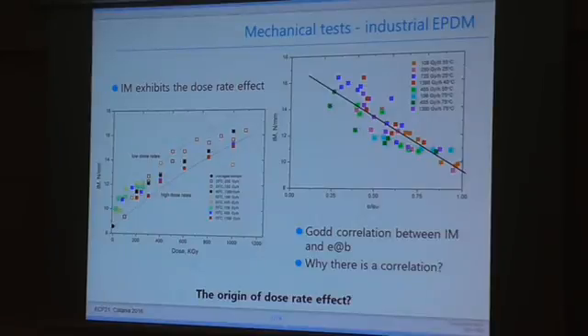Moreover, we observe a great correlation between indentation modulus and elongation at break data. And now, of course, the question arises: why do we have such a good correlation? You will see later on that this question is actually very related to the origin of the dose rate effect itself. So now I'm going to present the mechanism that can explain all of our data, and I would just like to mention that it is also supported by our chemical analysis, which is not presented here today.